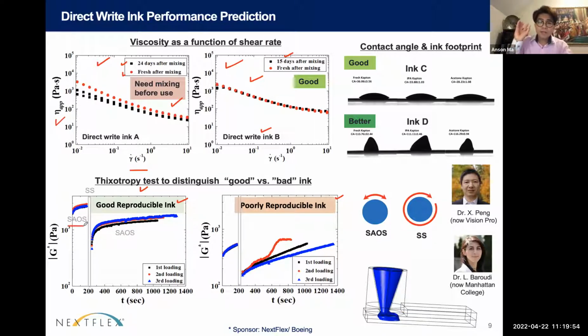What you do is apply a very small oscillation, and then measure the complex modulus of the material. After that, you apply a steady shear, meaning that you keep turning, so you try to mimic the shear process that is induced during the printing process. And after that, you switch back to the small oscillation just to probe how the modulus of the material evolves as a function of time.